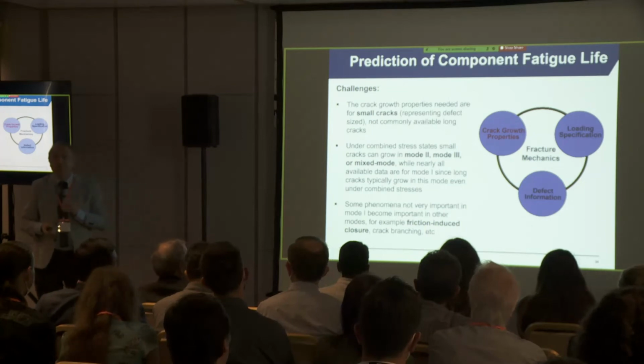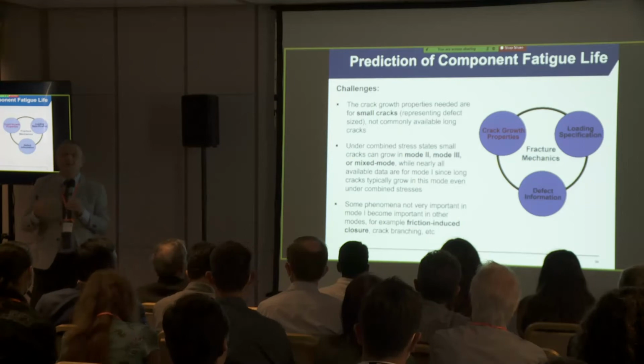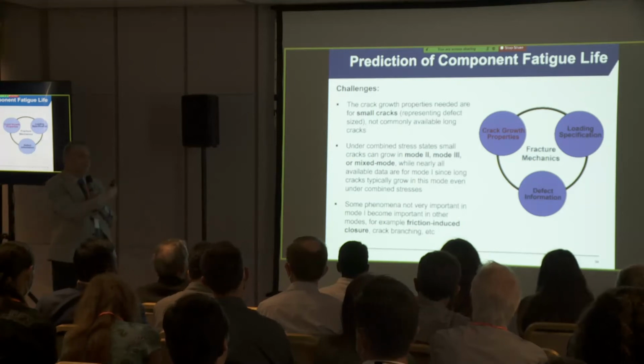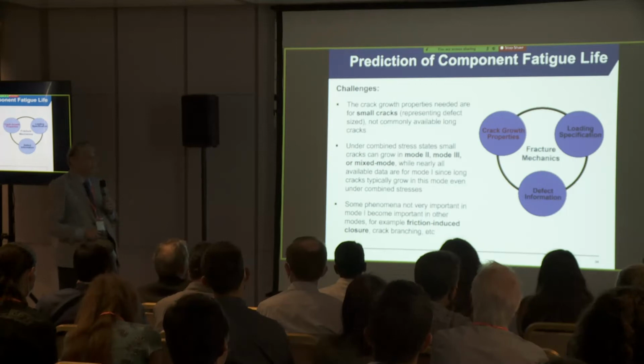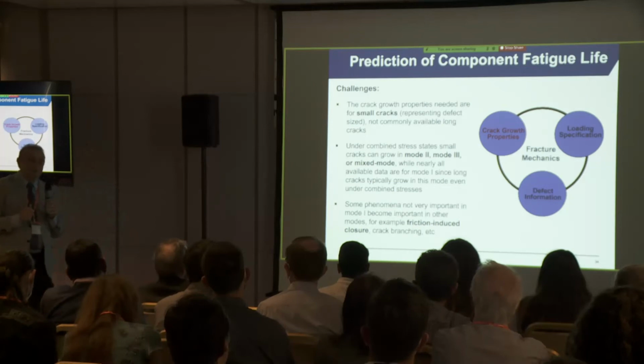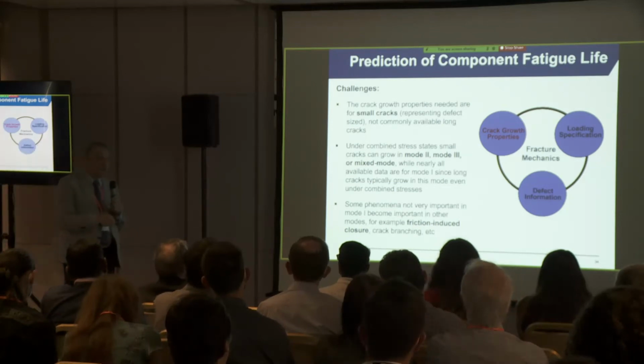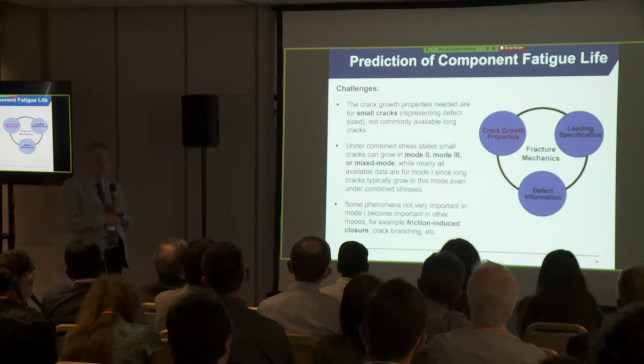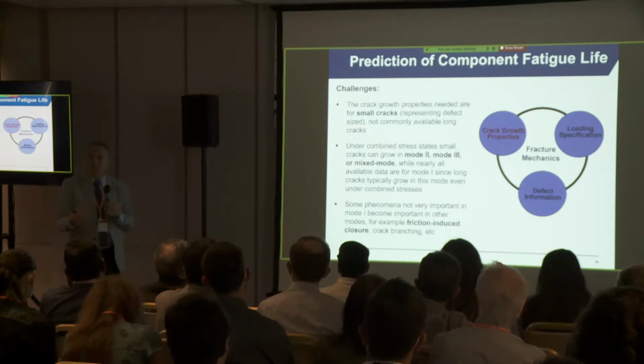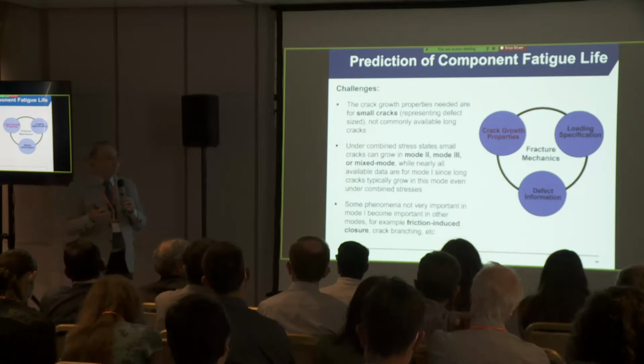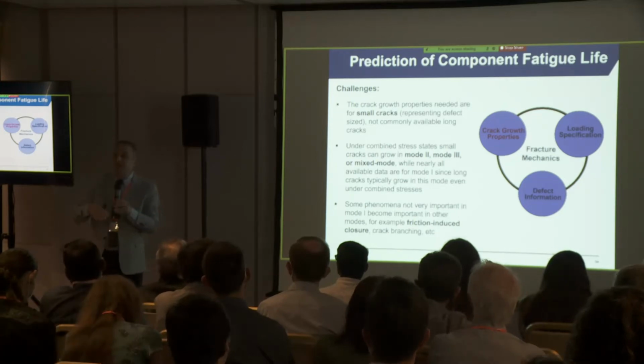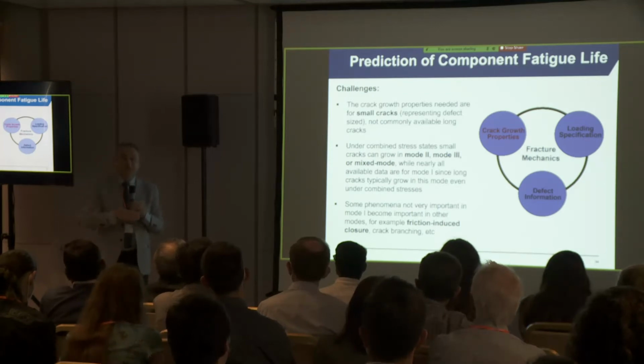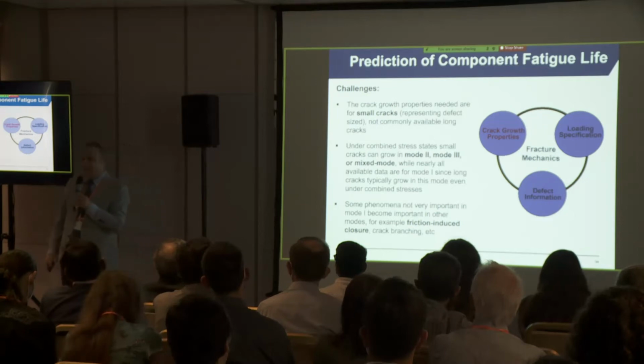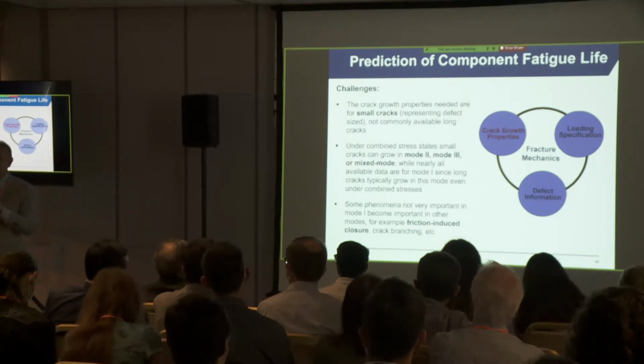What is typically available in the literature is for long cracks and for mode 1. When we talk about application to additive materials, we are talking about defects, therefore small cracks, and that kind of data is typically not available. And also not just mode 1, but mode 2, mode 3, and mixed mode. We normally don't deal with mixed mode crack growth because at macro scale, when the cracks are longer, usually they turn into mode 1. Even if you have multi-axial loading and you have mixed mode, they usually turn into mode 1. But when you are dealing with small cracks, that's not the case. You do have to deal with mixed mode behavior.